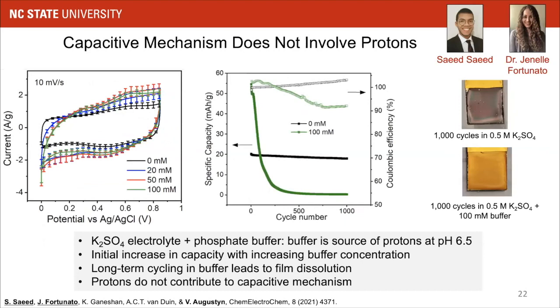Another question, since we were working with potassium sulfate aqueous electrolyte, was whether protons are involved in the capacitive mechanism. So in this follow-up study, what we did is that we added a phosphate buffer to the electrolyte while maintaining a pH of 6.5. Now the phosphate buffer serves as a source of protons. So there has to be a proton-coupled electron transfer reaction taking place at the interface. We observed that as we increase the buffer concentration, there's an increase in the specific current of the electrode.